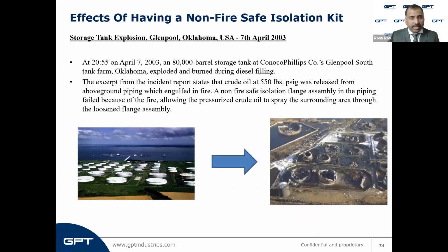One of the examples is the storage tank explosion in Glenpool, Oklahoma, USA, where the excerpt from the incident report stated that crude oil at 550 pound was released from above ground piping, which was engulfed in fire. A non-fire safe isolation flange assembly in the piping failed because of the fire, allowing the pressurized crude oil to spray the surrounding area through the loosened flange assembly. So it is an example of how things can severely go wrong and can cost millions of dollars. That is many, many times higher than the slight premium that needs to be paid for a fire safe isolation gasket.